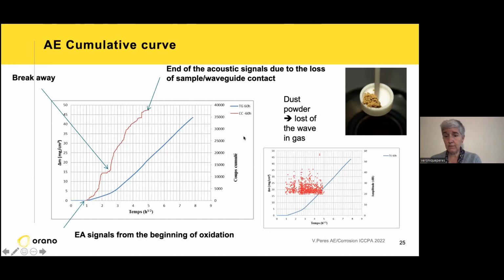Because you produce some dust and you lose the contact between the sample and the waveguide. So after a certain time it is not possible to obtain a signal. It's one of the limitations of this method. If you don't have a good contact between the sample during the corrosion and the waveguide, the sound cannot propagate via the waveguide, and so you cannot record it.